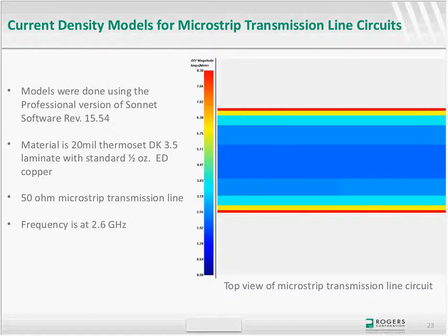In this case it was modeled using Sonnet software. Here we have a 20 mil material, in this case 4835, with a 50 ohm trace. The current density is highest on the edges. It's 8 times greater than what you will find in the center. That is what we mean when you put that plating on the edges of the trace where the current is going. We know that other than copper, silver is the only other metal that has better conductivity. Anything that you put on there will work against you in the sense of loss.